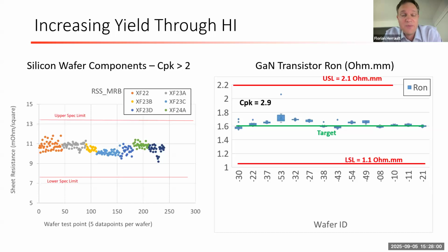So very, very high yield. The second aspect that has been a great surprise to us as we started to do this was that the transistor performance and the transistor yield has also gone up through our III-V suppliers, because now they only have to repeat the same device all over the wafer. And we see a lot more consistency within wafer and across wafers for key process specs. So here I took one of our commercial GaN supplier's on-resistance data. And what you can see is across a series of wafers, the Cpk is really high for this on-resistance, both within wafer and across lot.